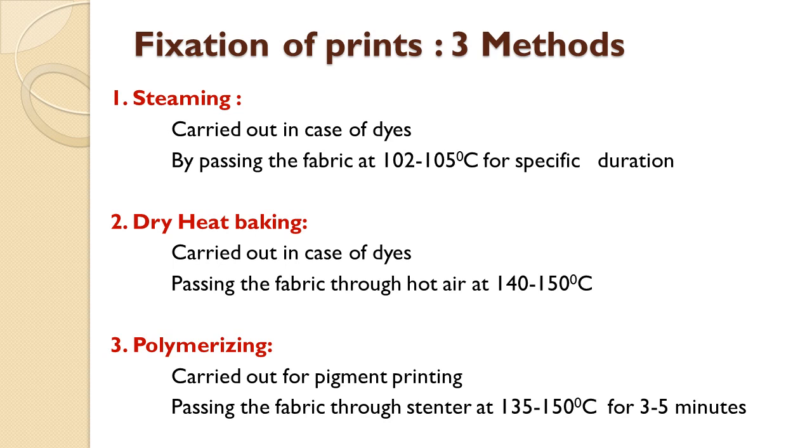In case of vat dyes on cotton, the duration will be up to 30 minutes. In case of acid and basic dyes for silk and wool, again the duration will vary from 30 to 45 minutes.